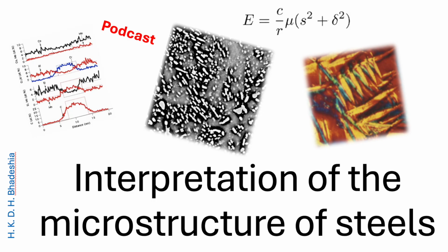So elements moving to where they'd rather be. Exactly. Carbon or other alloying elements will migrate. That means the product phase has a different composition than the phase you started with. In this scenario, any atomic correspondence between the parent and the product is completely lost. Okay, so if you see evidence of elements clustering or separating, you know you're on the civilian path. Now, what's the flip side?